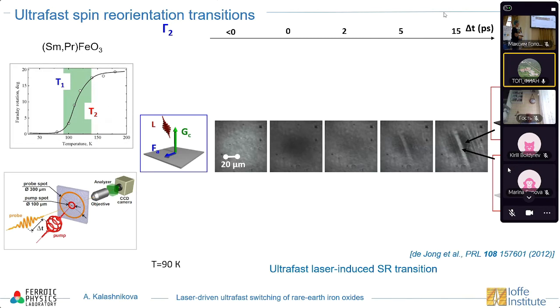This is the result. First, we use linear polarized light. So this is a negative time delay. It means that this is the image before the excitation. We have some gray area. It means that magnetization is in plane, and we don't see any magnetic contrast. But then after the excitation, after several picoseconds, we see some white or brighter and darker areas, which actually correspond to magnetization starting to reorient out of plane. And we get the Γ2 phase, with magnetization pointing a little bit up and a little bit down. It's actually what we expected, a multi-domain state.